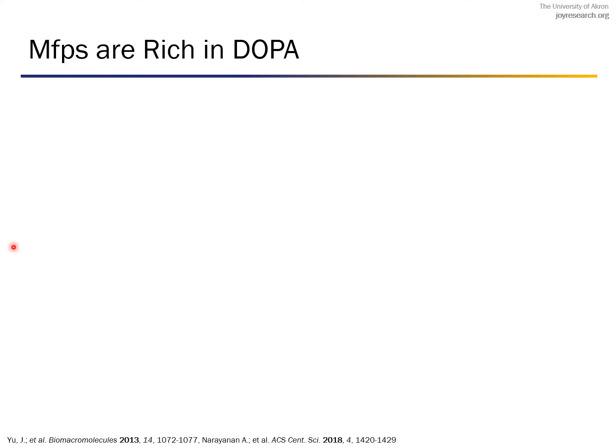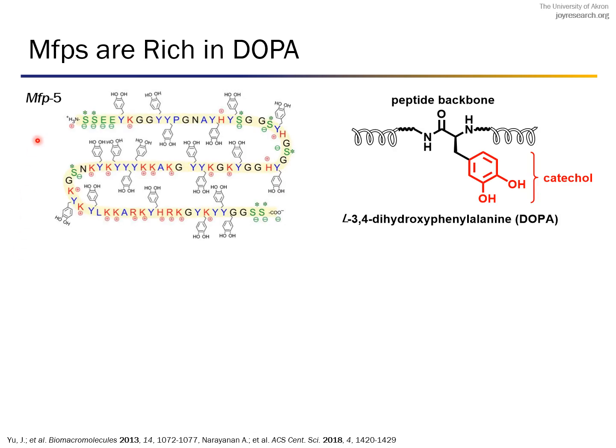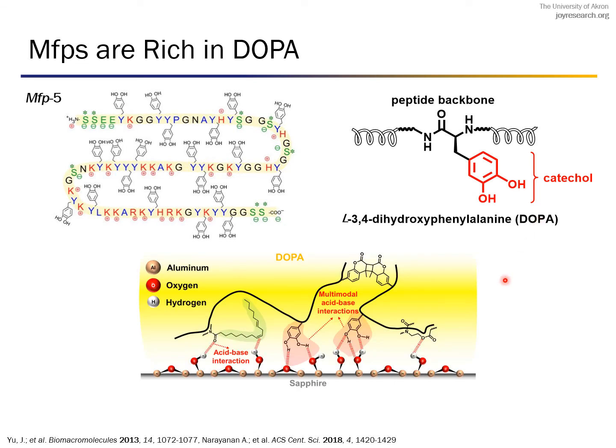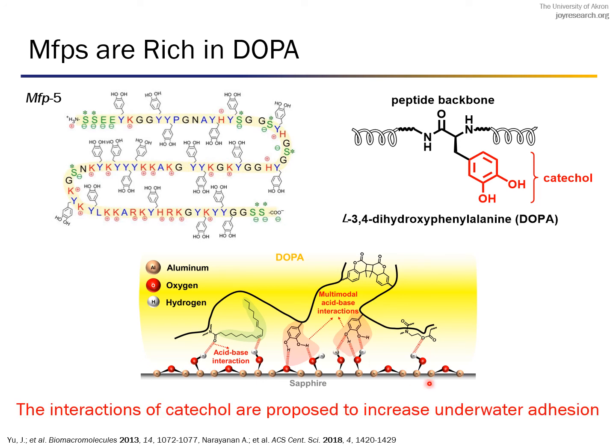So what makes mussel foot protein special? Here's the molecular structure of one of the mussel foot proteins. You can see here there is a series of post-translational modifications, which means this protein has been post-translationally modified to form 3,4-dihydroxyphenylalanine, also known as DOPA, with the catechol groups. In our previous studies, we have shown that these catechol groups can form multiple acid-base interactions in a localized site, called multimodal acid-base interactions. This allows these proteins to stick in underwater conditions.